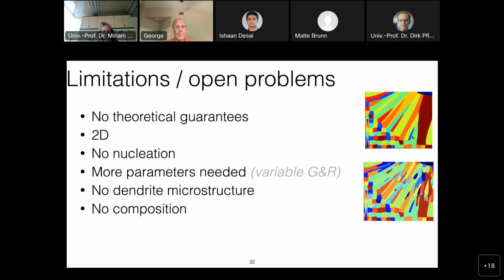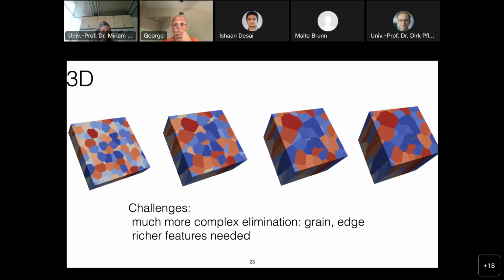So in the remaining time, let me actually show how this extends to a more realistic 3D geometry, for which we're going to use the same ideas, but the structure of the network will be a little bit different. So in 3D, again, we have some substrate of grain distribution. Again, every grain, essentially, is a crystal, and the color indicates different orientation, different growth direction. And as the crystals grow, some crystals disappear. For example, these small guys disappear, and then we have larger and larger grains until the solidification ends.